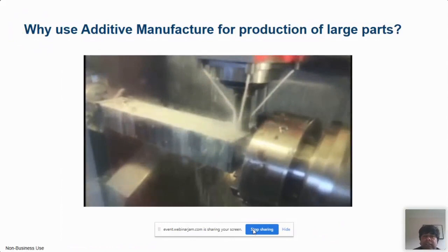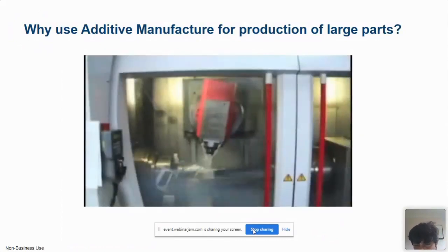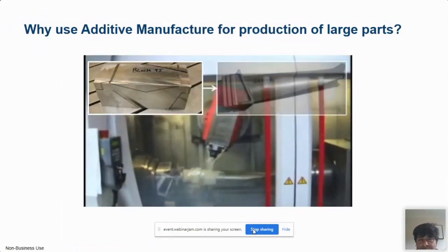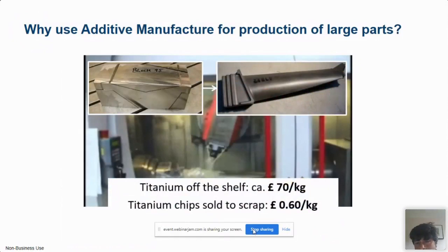So why use additive manufacture for production of large parts? This video shows the importance. You have seen at the beginning, there's a large billet which was then scooped out to form this part. When it comes to expensive alloys such as titanium, the cost is prohibitive, because you are losing a serious amount of metal. We call it the buy to fly ratio. So how much you are buying and how much is actually flying. And if you see in this particular example, there is a huge loss of metal because you are machining it out, and the scrap titanium is, as you can see, about 2 orders of magnitude cheaper than the titanium billet.